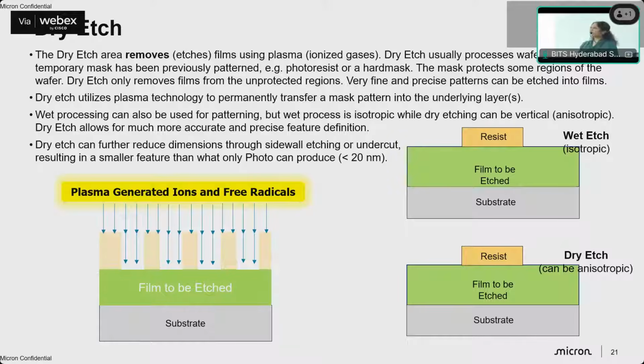Let's talk about dry etch here. Dry etch is one of the areas used to remove unwanted material from your process. It's basically a plasma. The ions that are created in the chamber are directed in a given direction based on the electric field at the bottom of the wafer compared to where the plasma starts. And that energy itself is enough to wipe out a certain area.